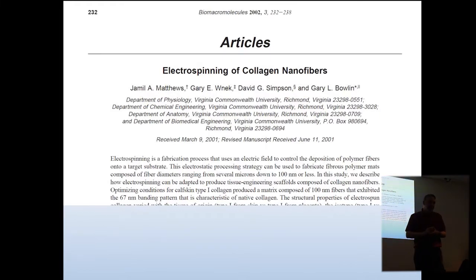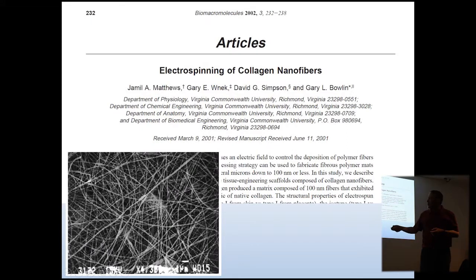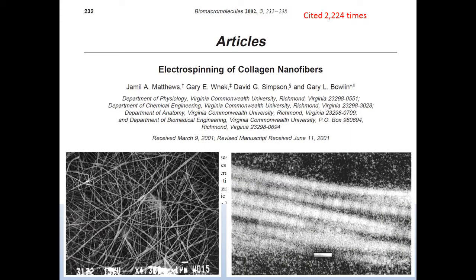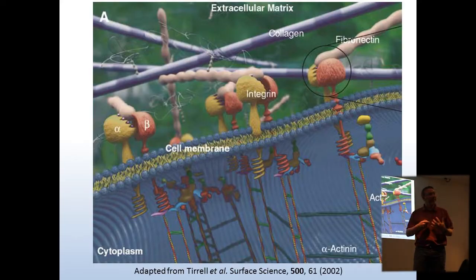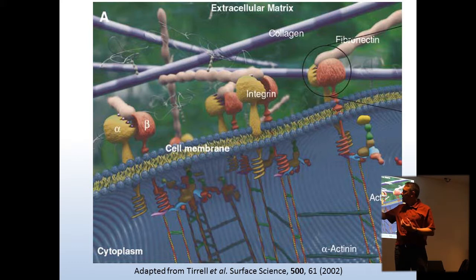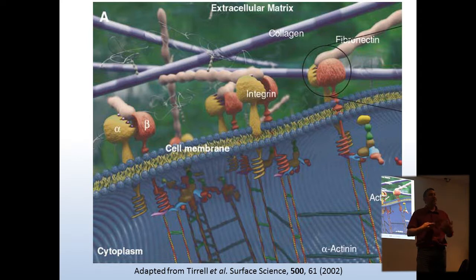One of the important papers earlier in electrospinning was this electrospinning of collagen nanofibers. These actually were nanofibers, I think about 100 nanometers in size. And you could electrospin this from hexafluoroisopropanol, HFIP. And this made nice fibers, and actually under the TEM you can see the repeat units of collagen. And so this started people thinking, wow, we can actually start electrospinning ECM. And if you have a look at the structure around a cell, you have these collagen fibrils that are connected through fibronectin, integrin binding sites and actin to cells. And so people were thinking, well, electrospinning makes small collagen fibers, so it can behave like an ECM.